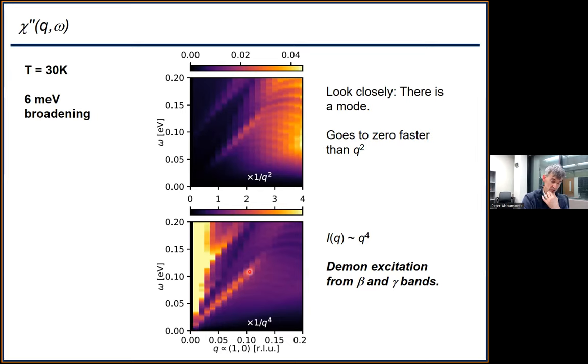And if you dig into the data and do some matrix decompositions of the susceptibility, you can show this comes about from an out of phase modulation of the beta and gamma bands. Both of these are electron-like bands. Neither one of them is a hole band, but they still form a demon. And the reason is because they beat out of phase by pi.